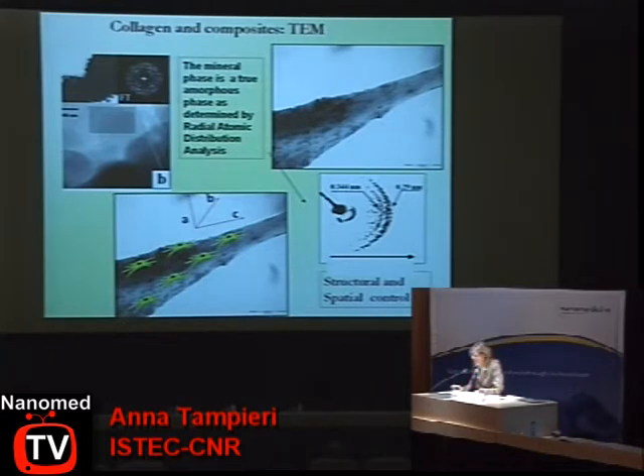If you look more in detail at the microstructure of this biohybrid composite, we can see that the mineralized fiber has the nanonuclei of HA completely merged in the fiber. And by X-ray flat chamber analysis, we can see that the C-axes of hydroxyapatite are growing parallel to the long axis of the fibers, as occurs in vivo. And this is extremely important since the AB axes of HA are exposed to be available for osteocalcin. And so the composite is characterized by high biomimetism and by high bioactivity.